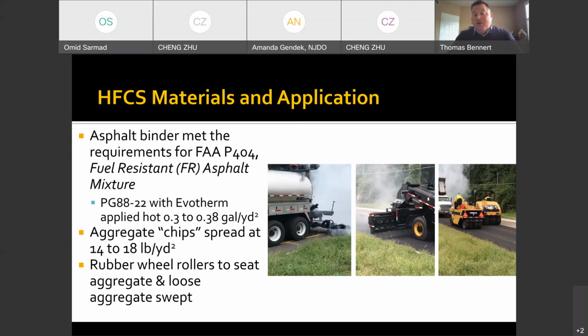So you can see the figure all the way to the left. That's the asphalt binder. That's the bonding system that's being applied to the existing pavement surface. The center photo are the aggregate chips that are being placed. They were spread down to about 14 to 18 pounds per square yard. The picture on the right are the rubber tire rollers that seat the aggregate in place. And then what I don't have a picture of is there's a vacuum sweeper that comes in behind after the roller to clean up all the loose aggregate to make sure that we're keeping, obviously, the people's windshields intact.